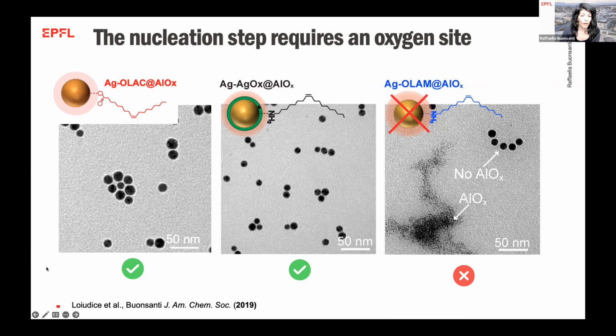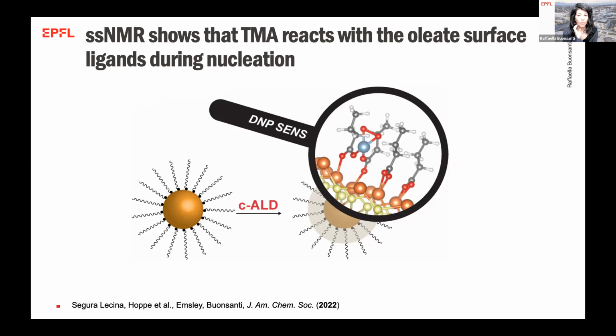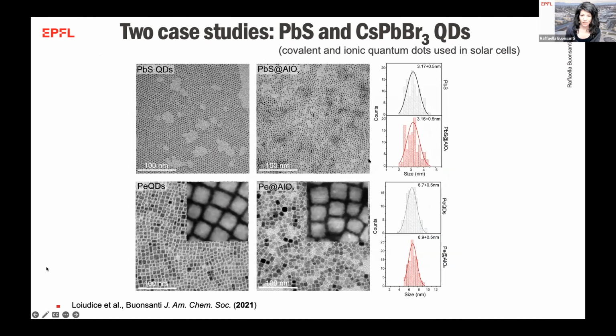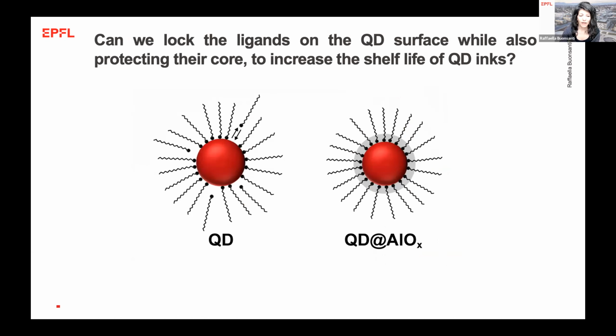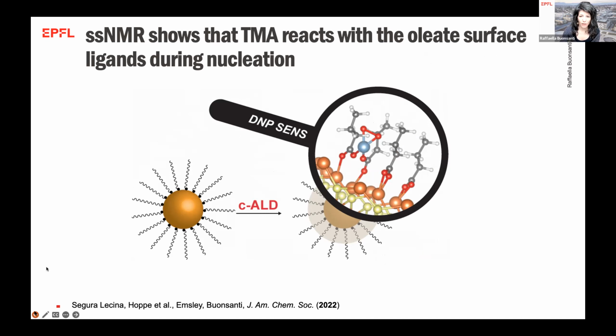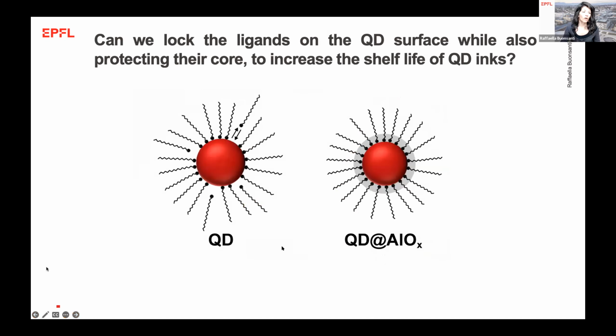Then if we don't have that, we can also have an oxidized surface, and also in this case, the shell grows. If we don't have any oxygen on the surface or in the ligand, it's clear at this point that the aluminum oxide nucleates separately. We also understood a bit more about the interaction of the oleate ligands and the TMA by performing solid-state NMR, which told us that indeed the ligands can act as nucleation sites.